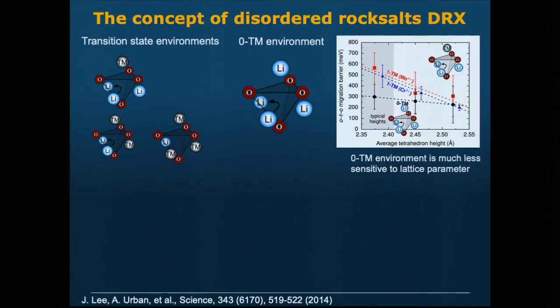And it turns out if you do ab initio theory, that's what you find. We artificially set up configurations with a lot of these 4 lithiums or 0 transition metal, as we call them. And again, this is now the size of the tetrahedron. If you reduce it, the activation energy goes up only by a little. Whereas if you have 1 transition metal there, it actually goes up a lot more. So the key for us to be able to work with condensed systems, systems that are much less sensitive to lattice parameter change, is to create mobility through these what we now call zero TM channels. And so how do you do that?